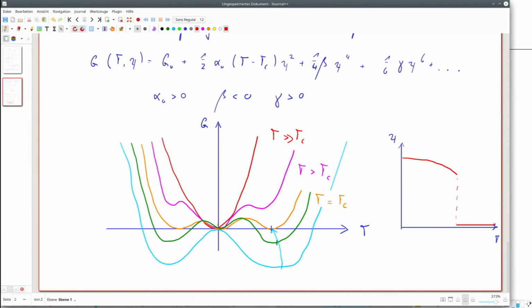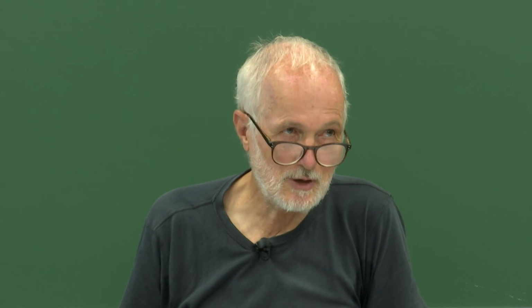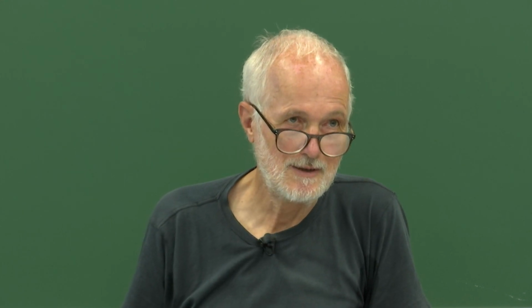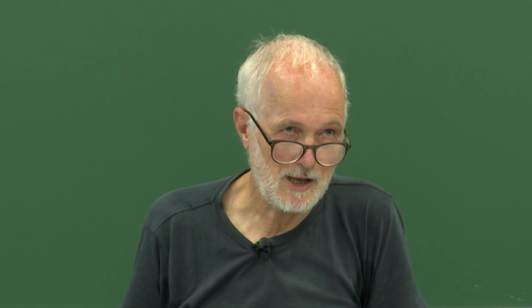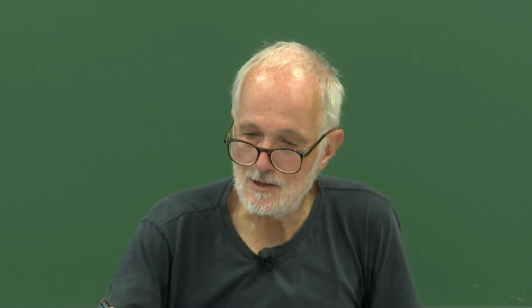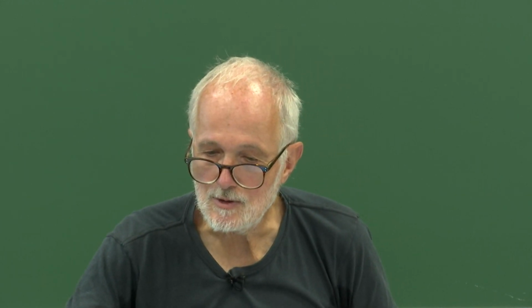How does this relate to what I said before, that first order phase transitions are related to a jump in entropy? I think it's more or less intuitively clear that entropy and degree of order are directly related. So if the degree of order jumps, we expect also to have a jump in entropy. So this would correspond also to the entropy.